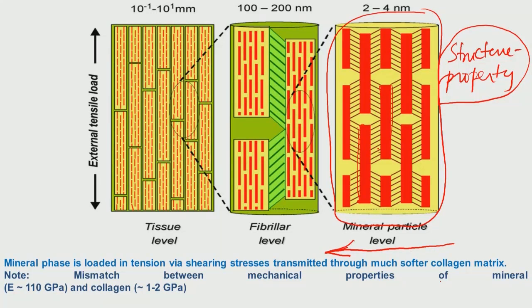So in this collagen bundle, there is some sidewise interaction also shown here. The sidewise interaction is essentially by weaker hydrogen bonding or van der Waals type of bonding. Therefore, at any given stress conditions, if necessary, this collagen bundle can slide over each other. The sliding of the collagen bundle is possible, and that leads to a certain element of deformation in the bone structure.